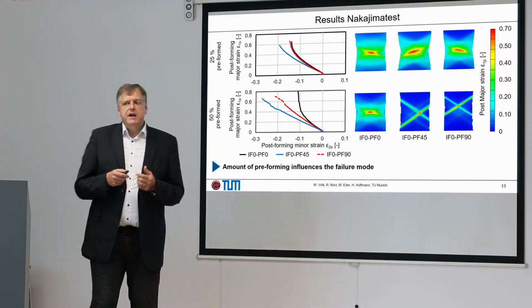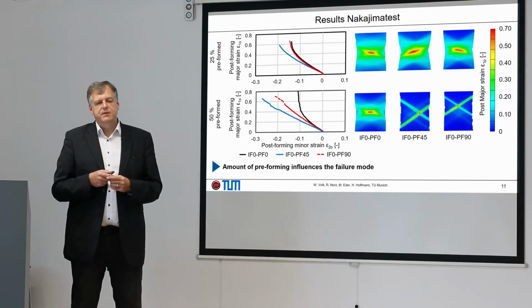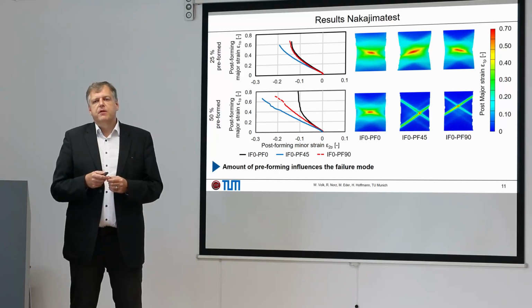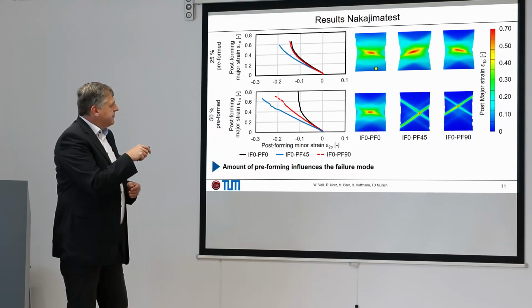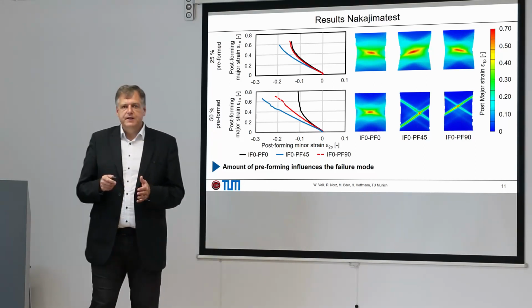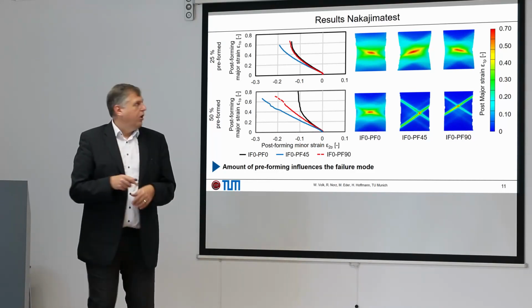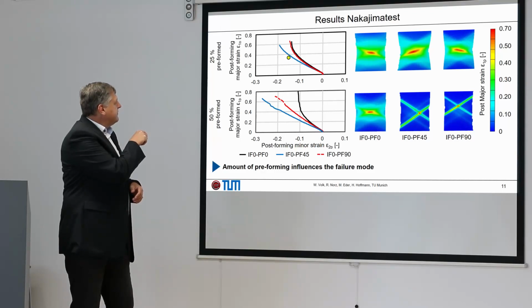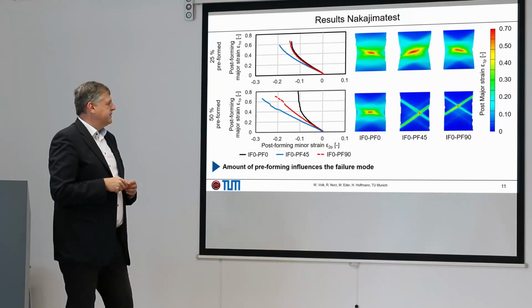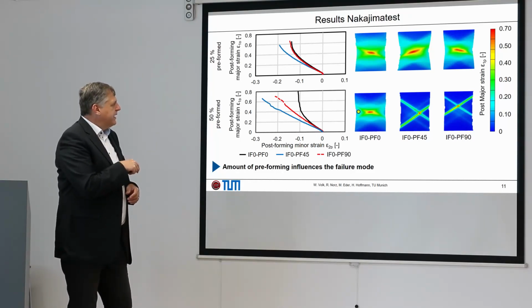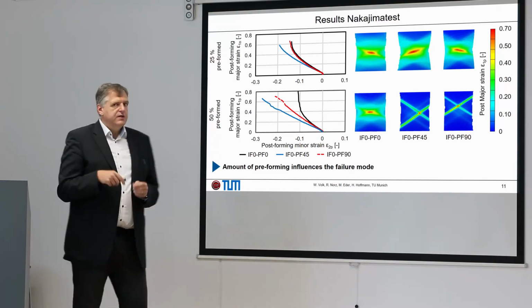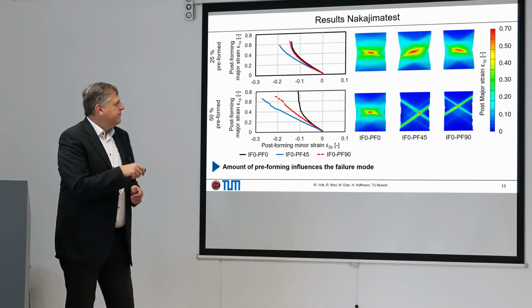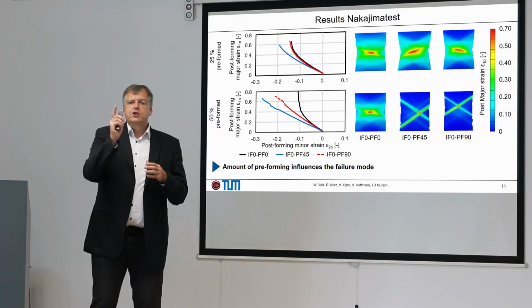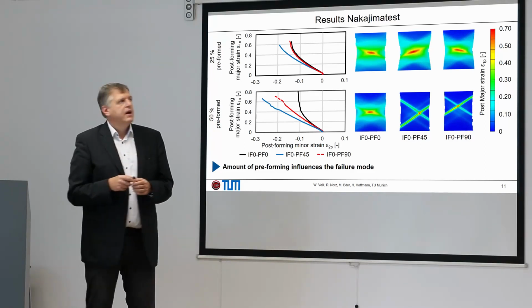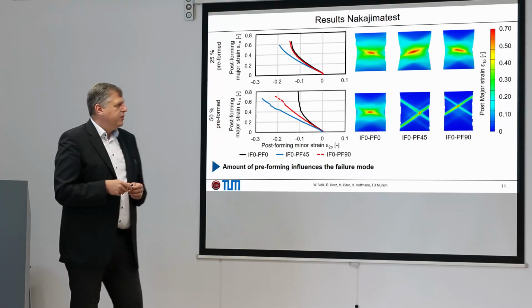Now, let's compare it also for the second group of specimen, where we have used a preforming step of only 25%. So with 25% preforming, we don't see this effect of shear localization. Always same behavior, start of diffuse necking and then localized necking out of the middle of the specimen. And when having the big pre-strain of 50%, here also in 45 and 90 degrees, we have the totally different failure behavior. So in the following, we describe this classical one, change to plane strain with failure mode 1, and this ductile shear fracture with failure mode 2.